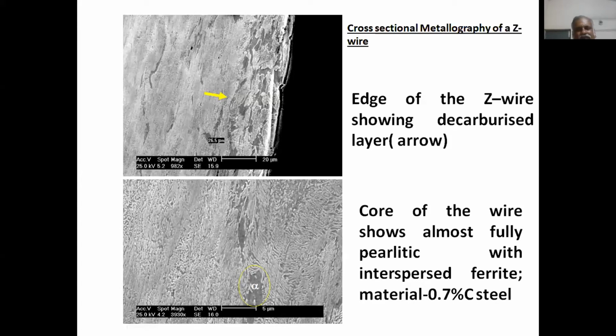But if you look at the edges, you find the structure is different. Microstructurally, the probe exhibits on the outer edge, up to about 25 micron, I have shown the micron here, and you can see here the width measured. The structure is around 50-50, that is 50% ferrite, 50% pearlite. That means it is 0.4% carbon steel. Basically, this is heat treated, and instead of 0.7% here, the edges have lost their carbon. What is it called? Metallurgists will immediately say it is decarburization. If decarburization is present, you will lose the carbon. If there is a carburizing environment, then it will become carburized. But this clearly shows decarburization has happened.